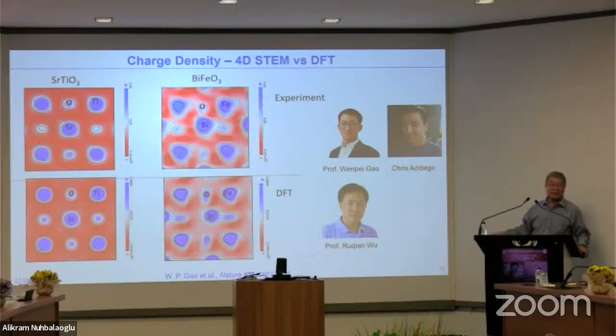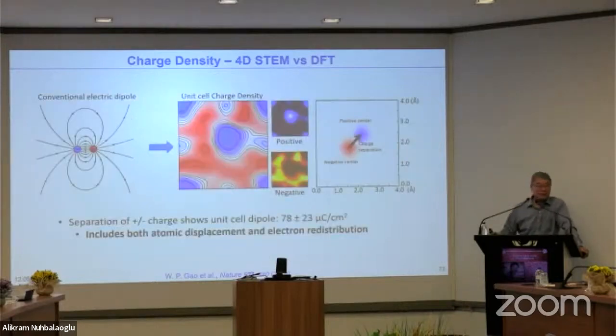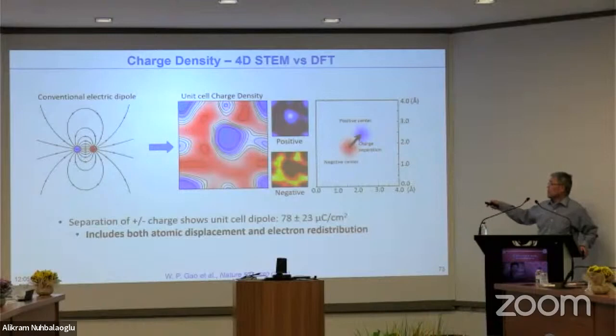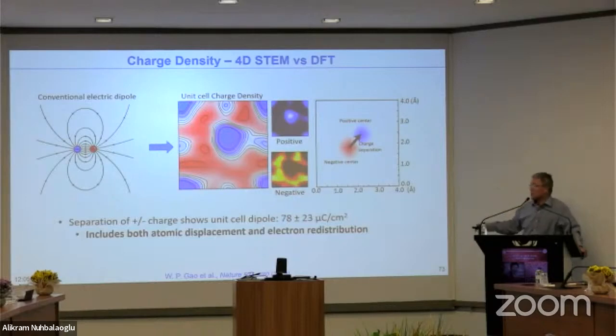But this is very encouraging. The charge density can be mapped using experimental methods. This applies to small nanostructures, and also to interfaces locally. By knowing the charge density, you can determine the center of negative charge and the center of positive charge, including ionic and electronic contributions. With this, we can determine the dipole moment for each unit cell of this material. This matches very well with the bulk value.